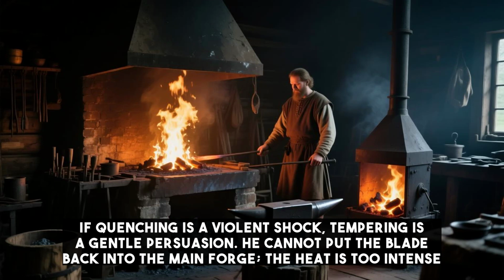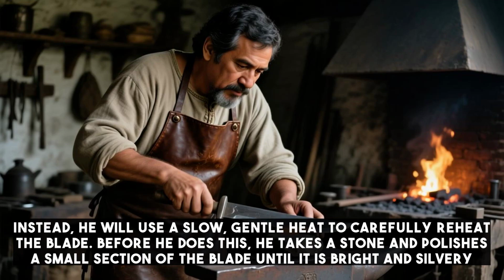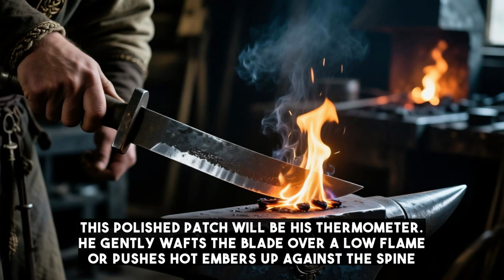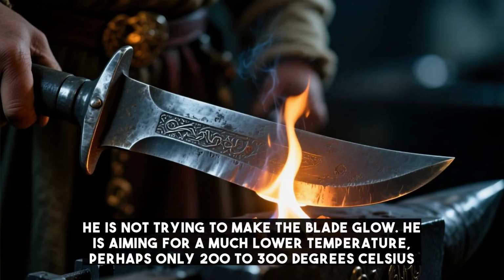He cannot put the blade back into the main forge, the heat is too intense. Instead, he will use a slow, gentle heat to carefully reheat the blade. Before he does this, he takes a stone and polishes a small section of the blade until it is bright and silvery. This polished patch will be his thermometer. He gently wafts the blade over a low flame or pushes hot embers up against the spine. He is not trying to make the blade glow. He is aiming for a much lower temperature, perhaps only 200 to 300 degrees Celsius.